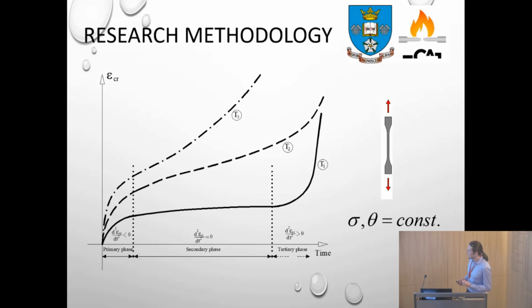As far as the creep tests that we've done, we've done basically constant stress and constant temperature creep tests, a series of them, and the general output of this kind of tests on metallic elements is the formation of primary, secondary, and tertiary creep phases. So the problem in the definition of a creep model for this kind of occurrence in strain is that you have a double S curve which changes phases at various points in time with respect to temperature. So it's very hard to define a unified analytical model to begin with if you have this kind of a problem that you have to solve.